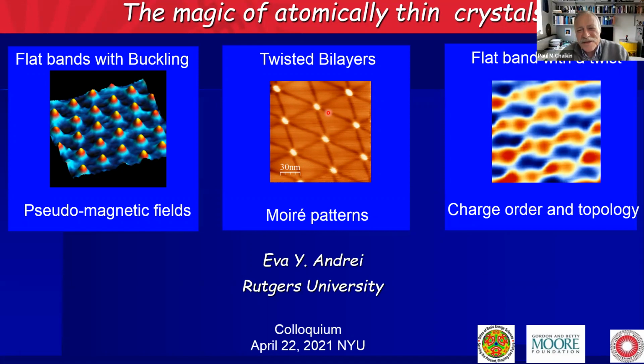Yeah, that always surprised me that it doesn't lock in. Because look, this is how we do it. You take one layer and you slice it in two pieces, and then you lift up the second piece and do parallel transfer on top of the other. And now we have a goniometer, something that allows us to twist the top layer and we control it to hundredths of a degree. Then we lay down and take advantage of the differential sticking. It likes to stick to itself more than to the boron nitride that I picked it up with. So it's kind of frozen in there.